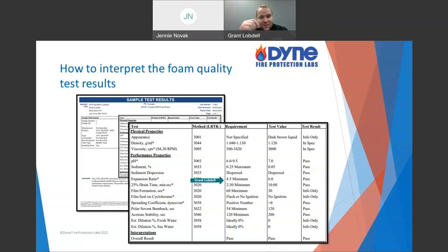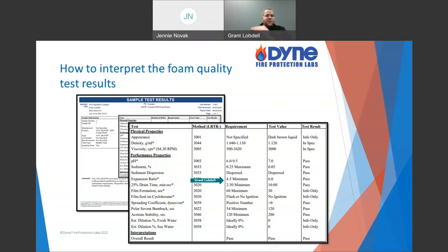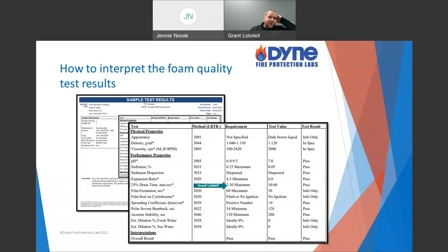With viscosity there's actually one case where it can go up within the first year. You test it, and the next year it went up, then stays stable. What happens is when the product is made and sent out the door, that polymer ingredient can continue to hydrate — absorb water. It takes a little time. So if you test it right out the door at 2,000 cP, then next year it's 3,000, and then stays at 3,000 — what happened is the polymer just fully hydrated in that first year. That's the only instance I can think of where something increases after sitting in the field.